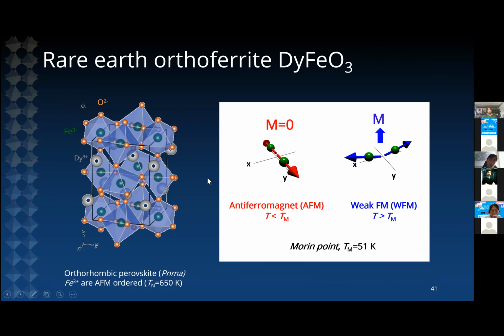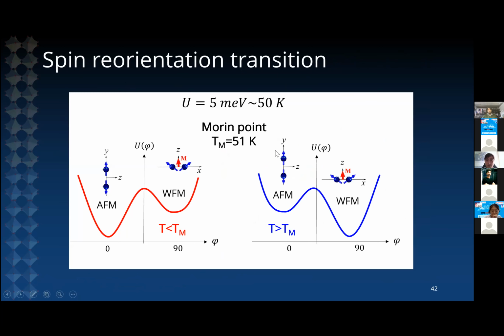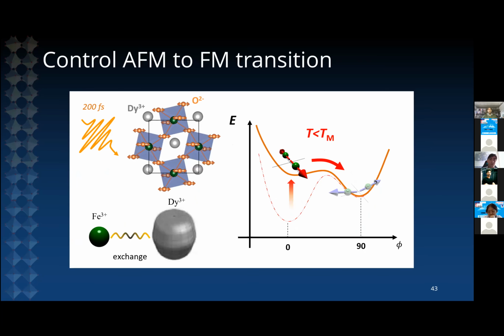So this is an orthorhombic system that has a transition from an antiferromagnetic state to a weakly ferromagnetic state, which is also known as a spin reorientation transition. So this is a first order type of transition characterized by the competition between two energy minima and an energy barrier of the order of a few millielectron volt, which leads to this Morin point type of transition. And the idea of our experiment was to modulate the crystal lattice of this material with resonant laser pulses, manipulate the energy barrier through a change in magnetic anisotropy, and induce the spin reorientation transition.